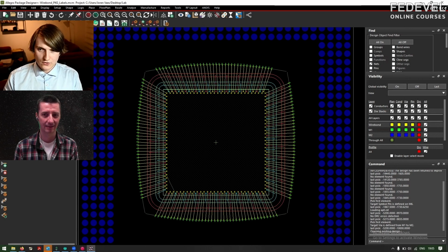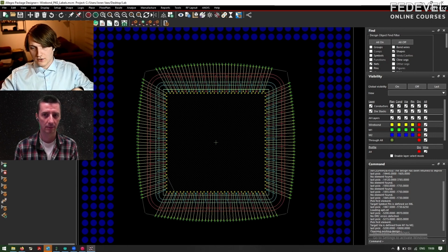for example, TSMC's CoWoS, which is where the packaging material, the packaging substrate, is made in the same way as a chip is made. So it's a silicon or a glass wafer, and then they etch and plate metals and make oxides and grow it that way. And then you can get extremely high densities.